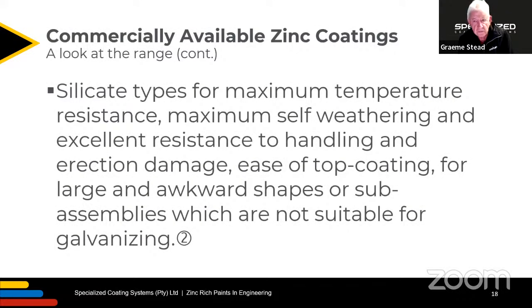Silicate types for maximum temperature. These are the inorganic zincs and the alkali silicates. Maximum temperature resistance, 400 degrees C. Maximum self-weathering and excellent resistance to handling and erection damage. Ease of top coating for large and awkward shapes or sub-assemblies which are not suitable for galvanizing. And often a structure will not fit into a galvanizing bath, and the size of the baths is the limitation in many galvanizing plants.